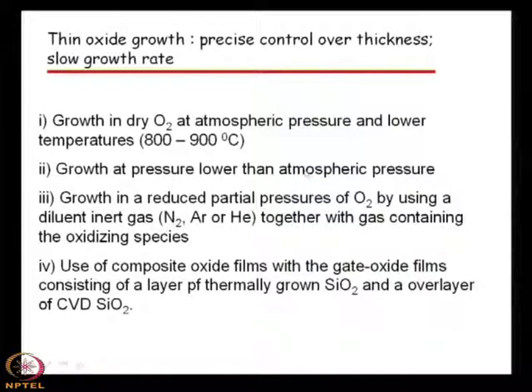So, then it becomes slower. At lower than atmospheric pressure, the rate will be less. Growth in reduced partial pressures of oxygen can be achieved by using a diluent inert gas. The inert gas can be nitrogen, argon or helium, together with the gas containing the oxidizing species. So, that means we can reduce the partial pressure. How to reduce the partial pressure? We can use some inert gas to dilute it, and that inert gas can be argon, nitrogen or helium. Then if it is grown at reduced partial pressure, obviously the growth rate will be very slow.